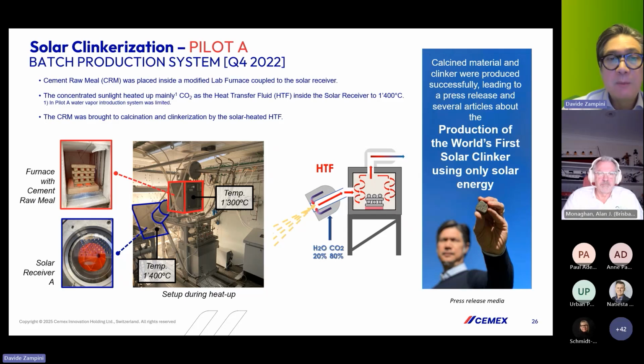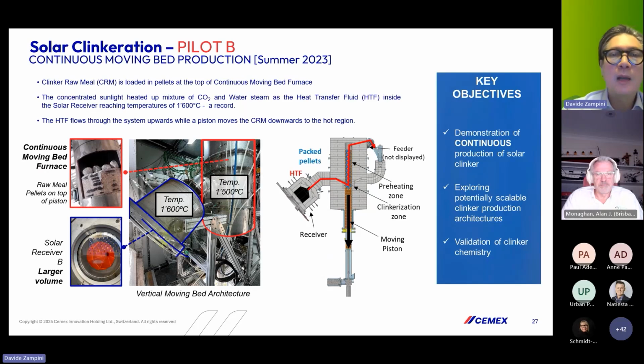So then we ran a small pilot at IMDEA. The first pilot was a batch process. Basically, we took the raw materials, put them in a furnace, and blasted it at 1,500 degrees, and using solar radiation, we produced the first solar clinker back in Q4 of 2022. And then, a couple months later, we said, okay, let's demonstrate that we can produce the solar clinker in a continuous way.